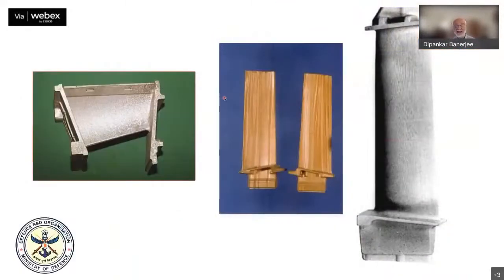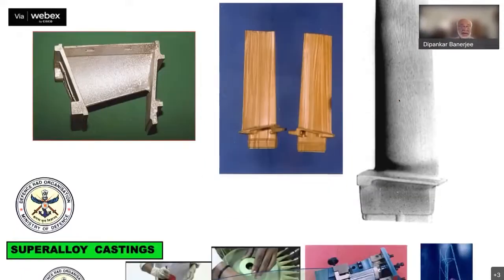And so we have to understand the substrate metallurgy. And part of that metallurgy is the improvement we have achieved in these materials through the casting process. And the casting process is required because we are making these complex hollow castings with the internal cooling channels. So we have gone from castings in which the grains are equiaxed in shape, you can see these fine grains here, to grains that are columnar in shape and oriented along the loading direction in operation, such that there are no shear stresses acting on the grain boundaries. And then finally, single crystals, which eliminate these weak grain boundaries altogether. So that is one part of the improvement that we have achieved.